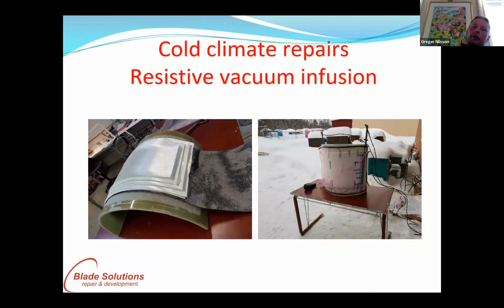That's why we put a typical blade heat system in the repair part. We have the laminate here that has some damage in it, and then we're going to put some repair material on top, and then we have a carbon layer here in between, in direct contact with the interface between the repair patch and the laminate. Then we can put the vacuum bag on it, connect it to power, and control the exact temperature in the repair.